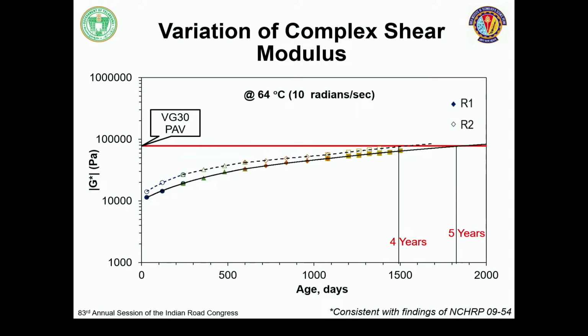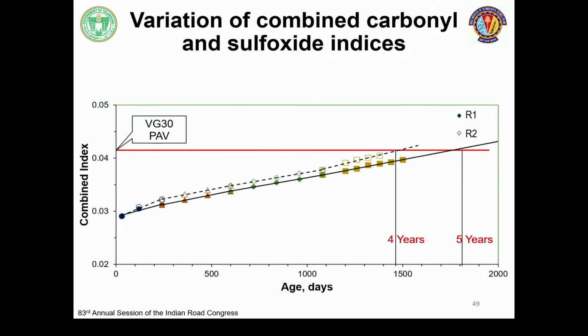Even in the NCHRP report 09-54, earlier they were mentioning it as between 6 to 8 years, but now it is 4 to 7 years. So road 1 was able to meet it in 4 years, and the other road in 5 years. That's our prediction. And it was also validated in the observation, where after 4 years we could see some initial cracks on the surface. And so was the combined index when we did the carbonyl and sulfoxide indices.